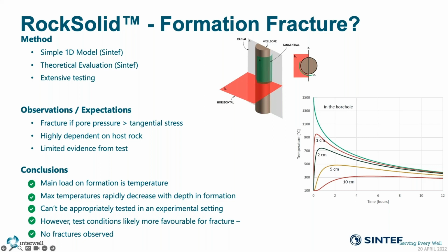However, what's removed is essentially replaced by the bismuth alloy that we create, due to its low viscosity and ability to flow. So any kind of pore space in close proximity is filled with the barrier elements, the bismuth alloy, as a result of that reaction.